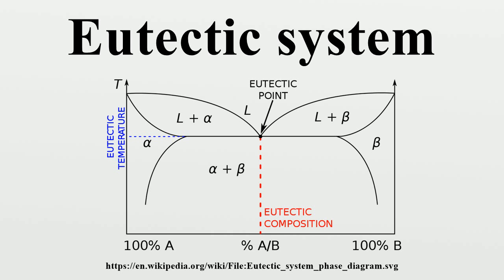Solar salts, 60% NaNO3 and 40% KNO3, form a eutectic molten salt mixture which is used for thermal energy storage in concentrated solar power plants. To reduce the eutectic melting point in the solar molten salts, calcium nitrate is used in the following proportion: 42% Ca(NO3)2, 43% KNO3, and 15% NaNO3.